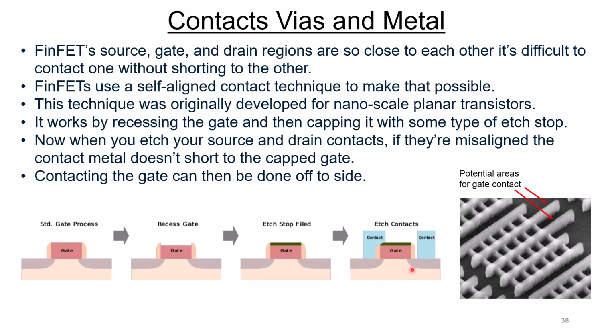And again, let's take a look at this diagram down here, and we can see how this works. This is done for a planar device, but it would be similar for the FinFET. We come in here, we define our gate. We recess the gate, and we put an etch stop on top. Now when we come in to create the contacts, the source drain contacts, if they're misaligned, this contact will not make contact to the gate because there's a material in the way here. And you can contact the gate off to the side. So in this case, our gate contact would be maybe off to the side over in this area here, and allow for the source and drain contacts to be close to the gate but not making direct contact to the gate.